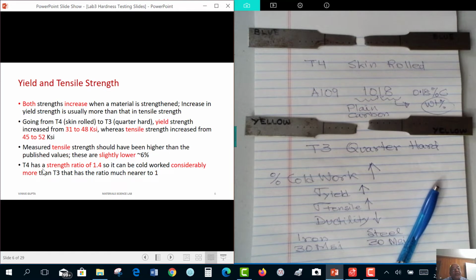Now, T4 has a strength ratio of 1.4, so that means it can be cold worked considerably more than T3, which has a ratio nearer to 1. It still can be cold rolled more, as we know, because it is only quarter hard, so its strength ratio was 1.1 or so.